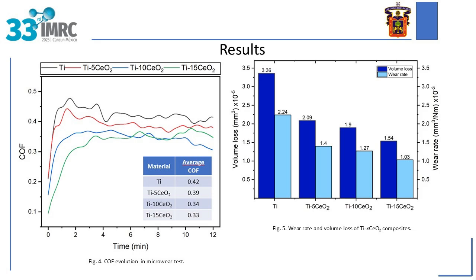Subsequently, the volume lost in each footprint was calculated using an optical profilometer. Archard's equation was then used to calculate the wear rate. After obtaining the results for the 4 samples, it was determined that the trend is the same as that of the friction coefficient, with the wear rate decreasing as the ceria content in the samples increases.